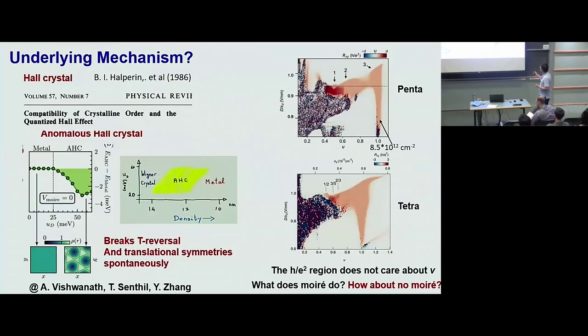And in our case, as you can see, the pentalayer and the tetralayer have slightly different twist angles. The pentalayer, this integer state, stops at roughly filling factor 1 and doesn't really go beyond filling factor 1. While in the tetralayer device, due to the different twist angle, this integer quantum anomalous Hall state actually protrudes out. It reaches a filling factor of something like 1.3.